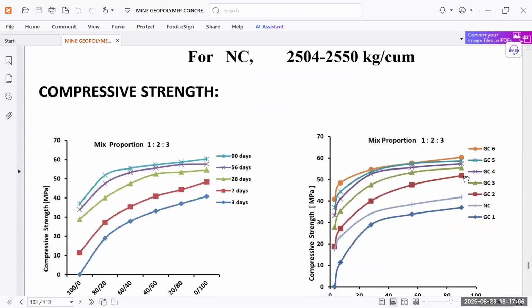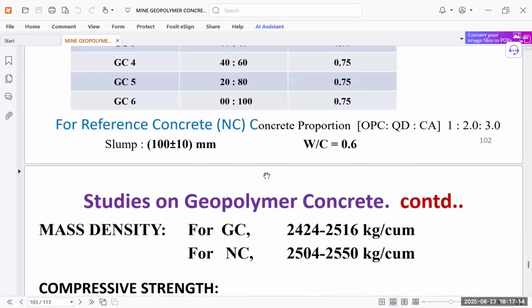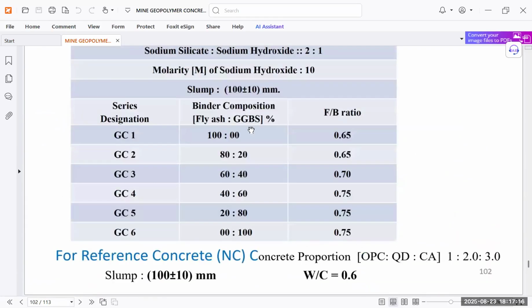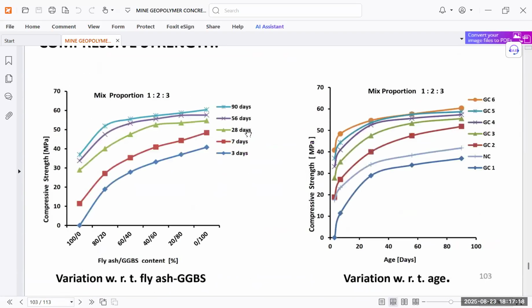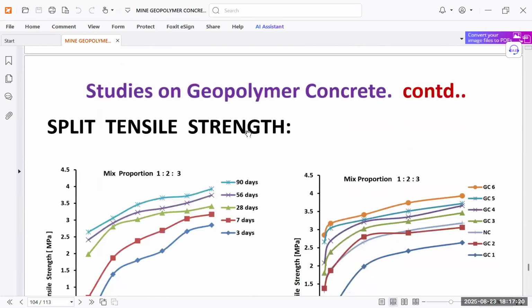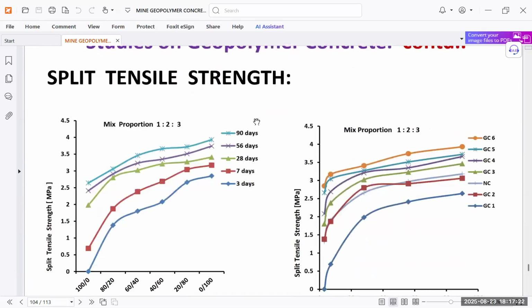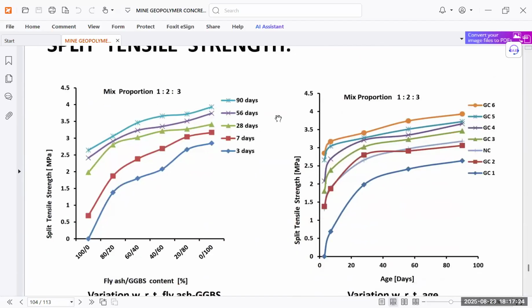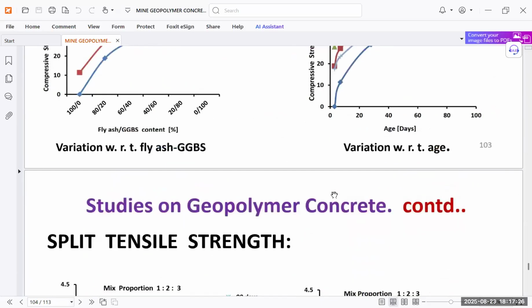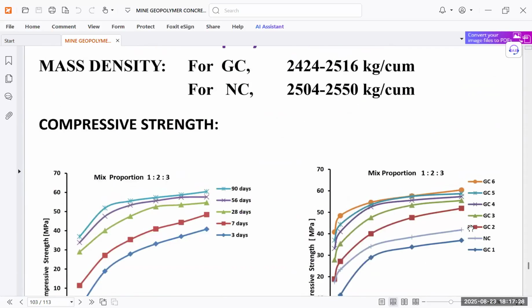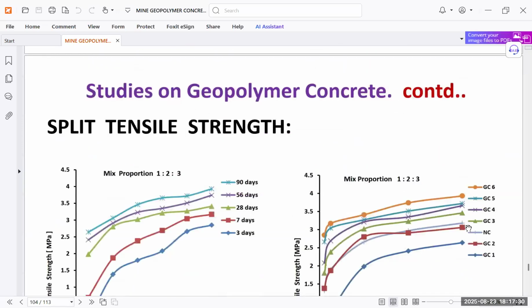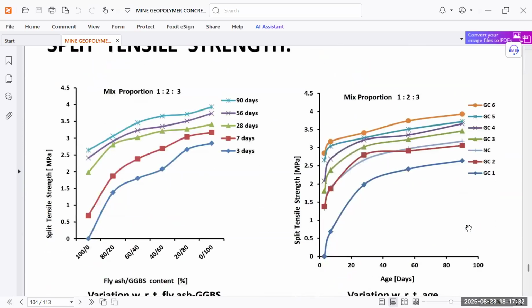In both cases, you can see that we can get more than normal concrete strength in geopolymer concrete by varying the mix proportion, by varying the fluid to binder ratio, and by varying the fly ash to GGBS content. So that is very important. Split tensile strength is also good with respect to normal concrete. So we can say that properties are as good as normal concrete. It is not very much less in the case of geopolymer concrete.